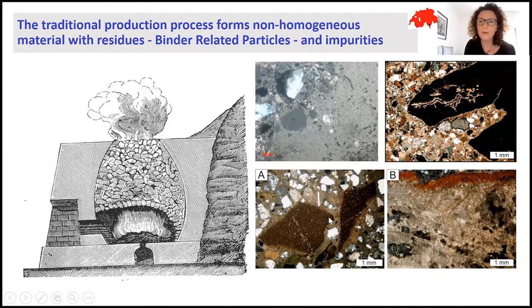And we have the underburned, which are particles that are far from the source of heating, and so they did not reach the correct temperature to be reactive, and they remain as witnesses of the original stones that were used for the lime production. This information is also useful because I can understand which kind of stone was used, for example for provenance study, but also to have more insight about the binder characterization, which is not always so easy with the microscope.